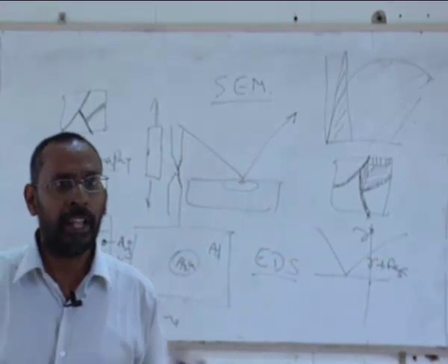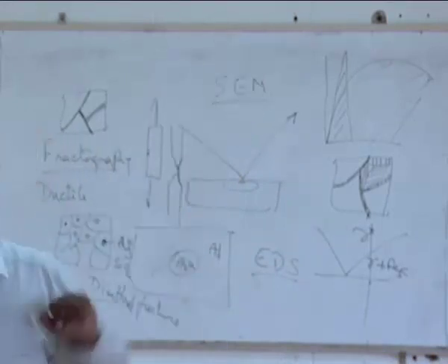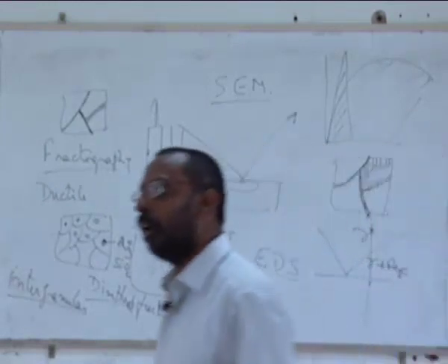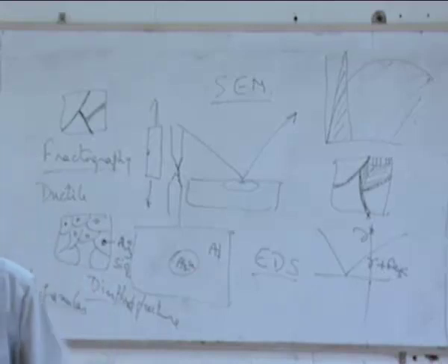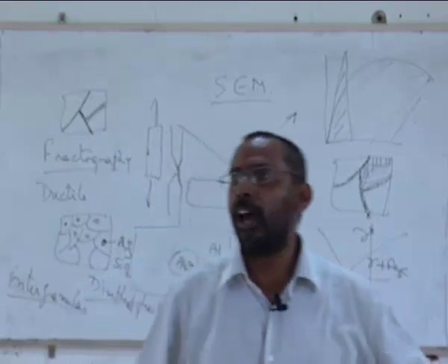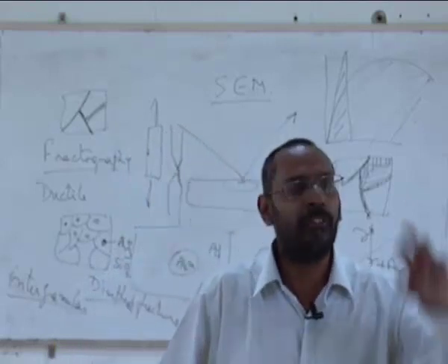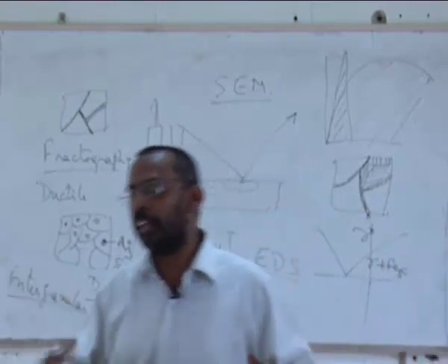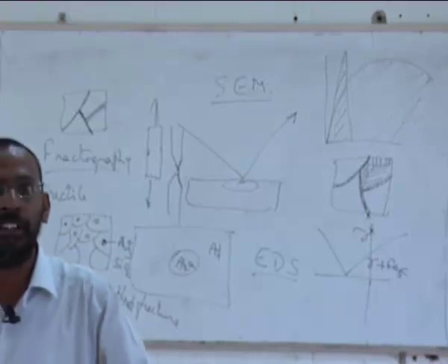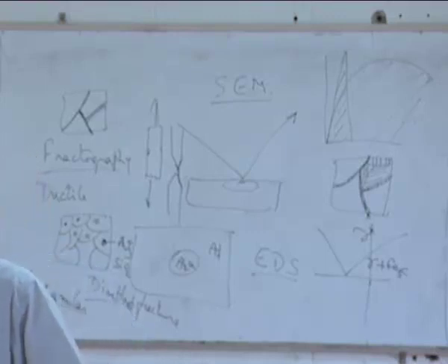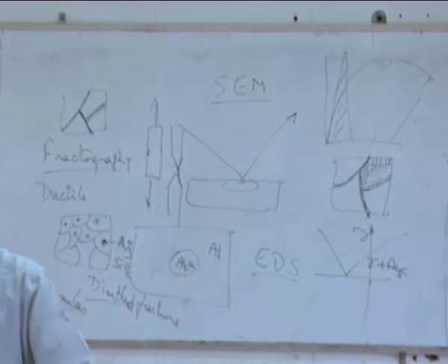If it is by explosion, then the crack initiates and propagates very fast. And by looking at how this crack propagation is on the fractured surface, you will be able to know whether it happened by explosion or because there are some inclusions inside, let's say, the aluminum alloy which is used, because of which the crack initiated. And there are engineers who are supposed to test every day before a passenger goes into the aircraft. If some engineer did not bother about it much, then obviously there were cracks.